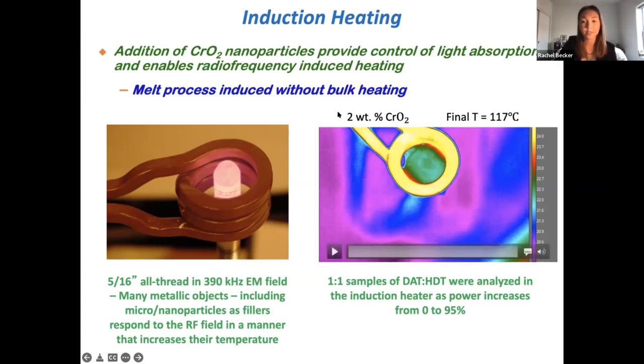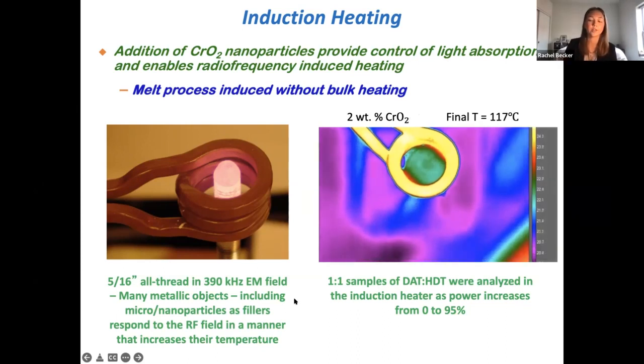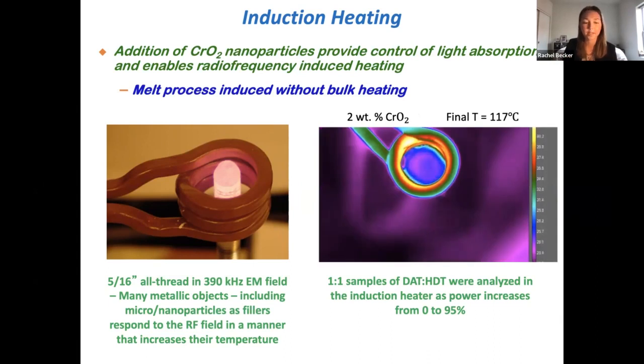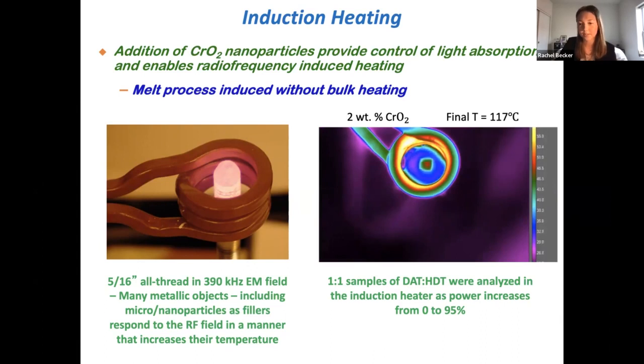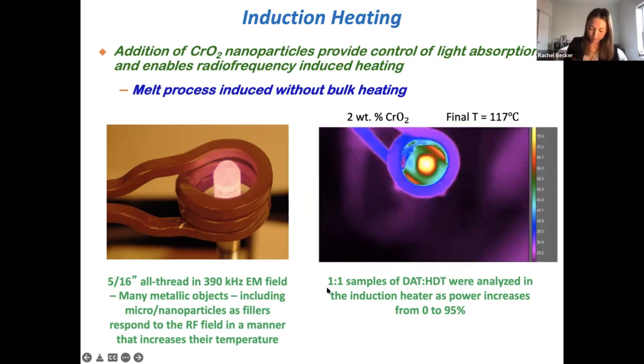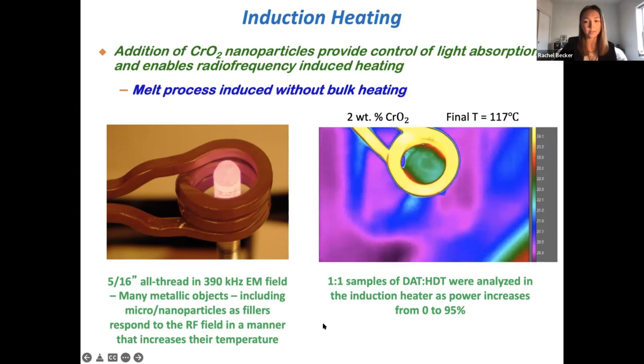So on the right side of the screen, we have that same induction coil with a 3D printed sample containing 2 weight % of the metallic chromium oxide nanoparticles. And as the induction coil is turned on from 0 up to 95%, we see that the sample in the middle gets heated all the way up to 117 degrees, which is more than enough to melt the polymer system. So this basically proves that the material system can be used for 3D printing, cast molding, with a way to locally heat the mold out of the cast.